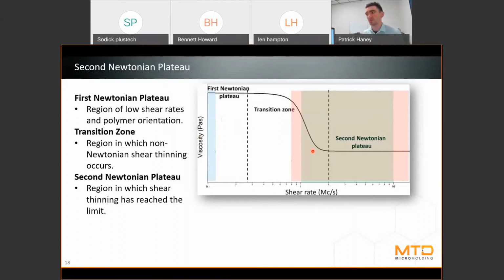Then we move to the transition zone, right? This is the region where non-Newtonians start to shear thin. Shear thinning is just the concept that results in a drop in viscosity because of the reasons we've discussed. Okay, so most of the injection molding industry exists somewhere in this transitional zone, because the flow channels are large enough to allow us advantages to shear thin, but we haven't maximized or reached the limit of that shear thinning.